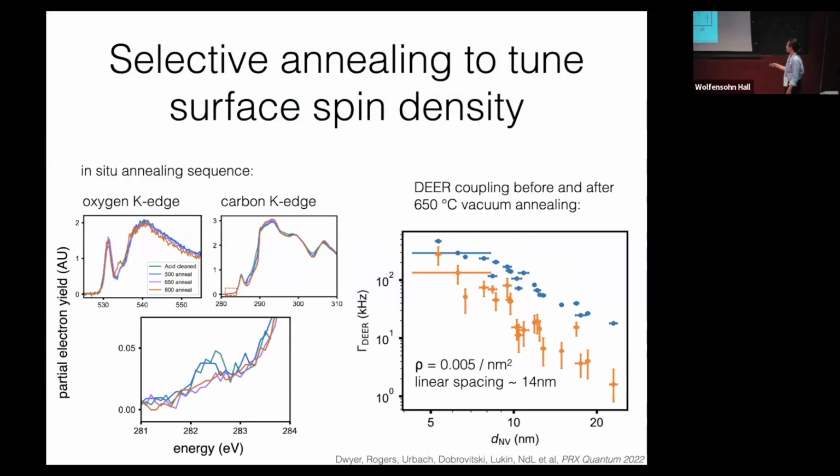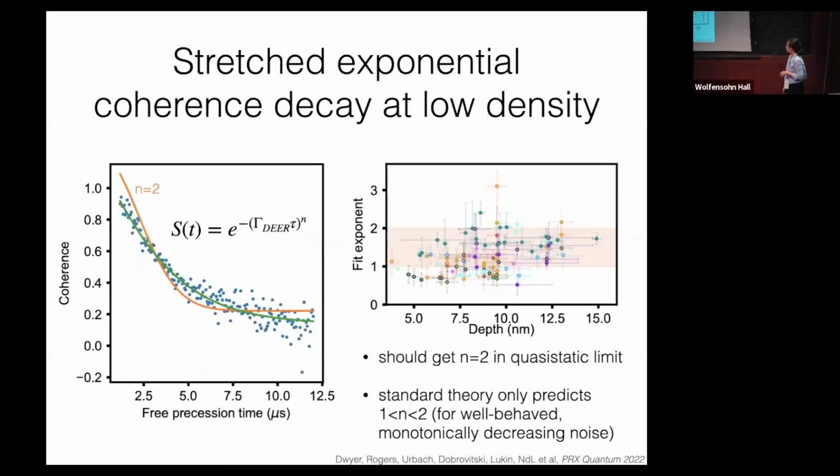It doesn't matter what the puzzle was, but we had this long-standing puzzle in the field that none of these numbers actually made sense. The resolution to the puzzle, I'm just going to give away the story right now, is that these surface spins can hop around and reconfigure. Once you put in configurational averaging, it all works out nicely, and that gives you these nice scalings with distance that are all sort of rational.